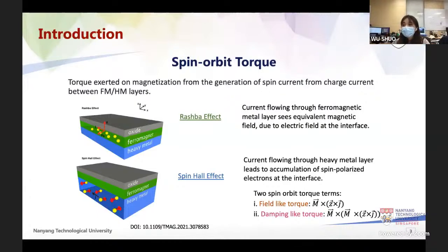This spin current is generated mainly from two spin-orbit coupling phenomena. First is the Rashba effect, which occurs in the FM layer. The current flows into the FM metal and sees an equivalent magnetic field due to the electric field at the interface. The second one is the spin Hall effect, which occurs in the heavy metal; the current flows through the HM layer, leading to an accumulation of spin-polarized electrons at the interface.